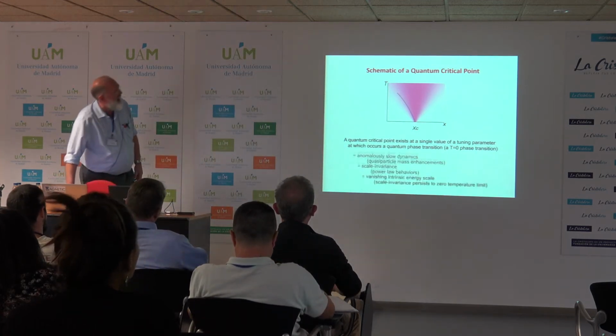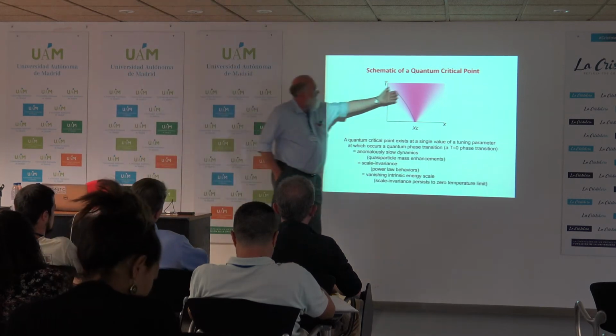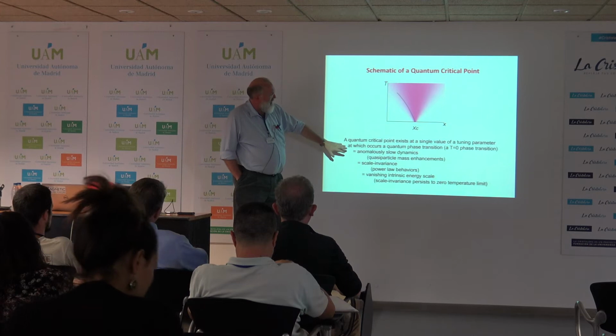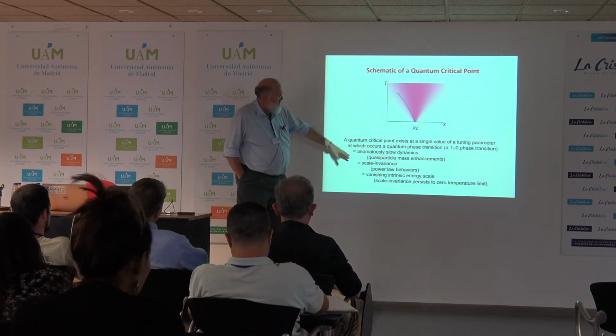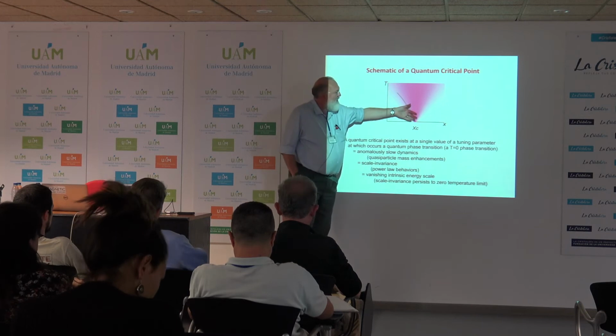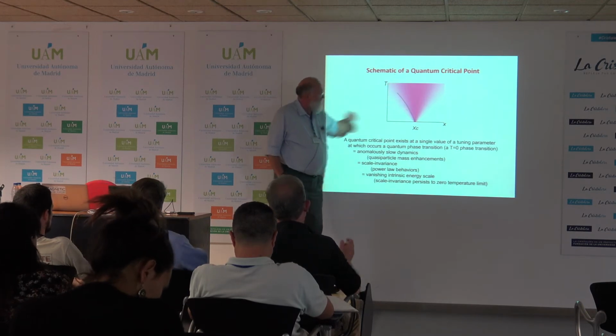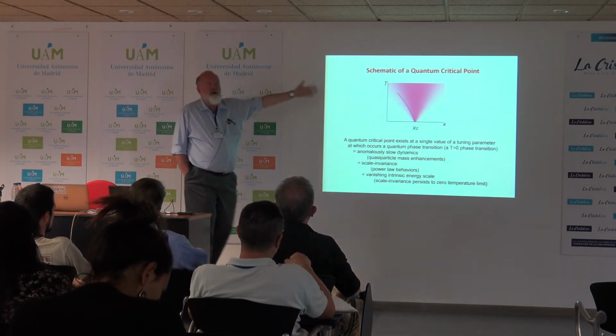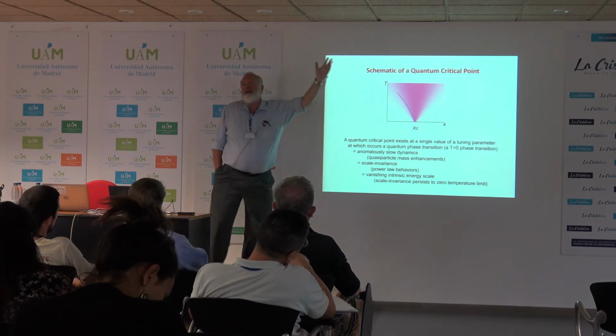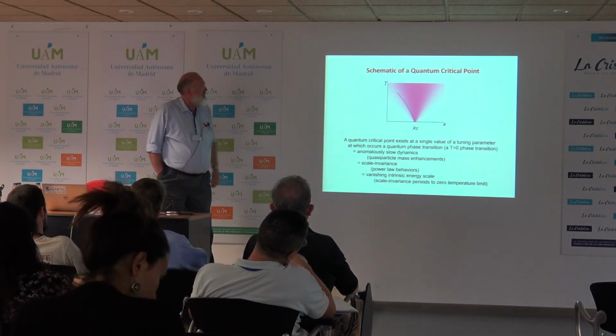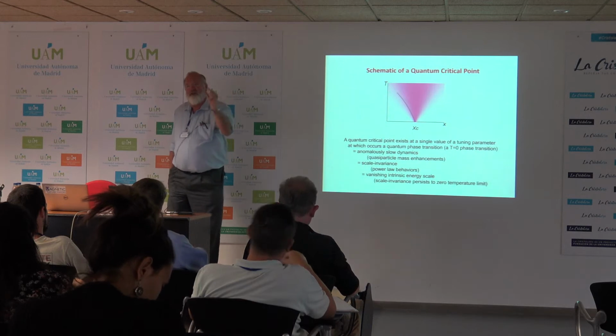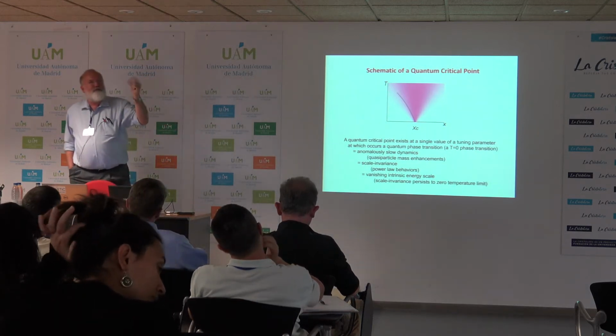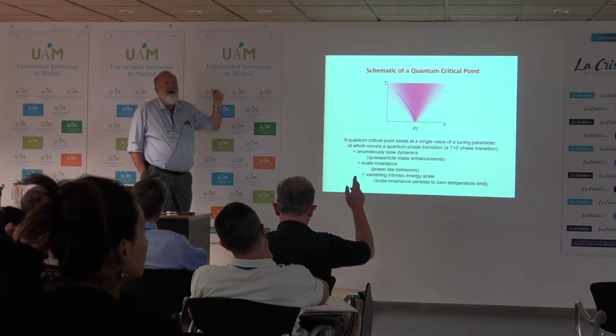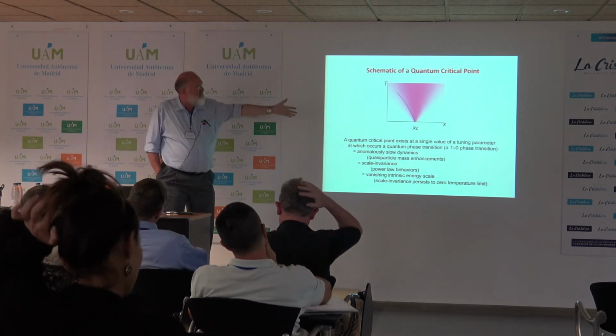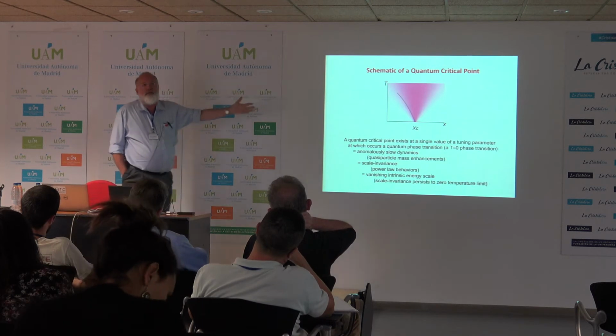And then on top of that, in this region that's shaded pink here, you get anomalously slow dynamics, quasi-particle mass enhancement. You get scale invariance, which would be power law behaviors. And perhaps the linear in T is a quantum critical behavior. It initially was thought to be insane to talk about quantum criticality up to 800 Kelvin. But I think it's an active discussion now. You know, the critical regime around phase transitions, for thermally driven phase transitions, is often just a few parts in 100 or a few parts in 1,000 of the region around TC. And this would postulate a huge regime of critical behavior.